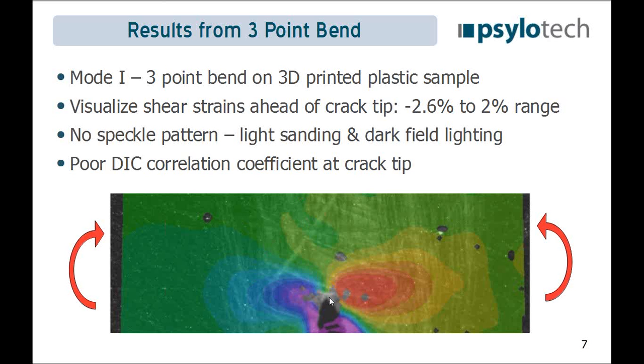Another thing I want to point out, which will be interesting for later, is that the VIC2D Correlated Solutions software for digital image correlation wasn't really able to do a good job in the middle where the crack was being created, because DIC doesn't work very well when new features show up in the images. I'll talk a little bit more about that in an upcoming slide, but I just thought that was an interesting result. These are the kind of pictures you might see in a textbook, but there you have it in your experiment.